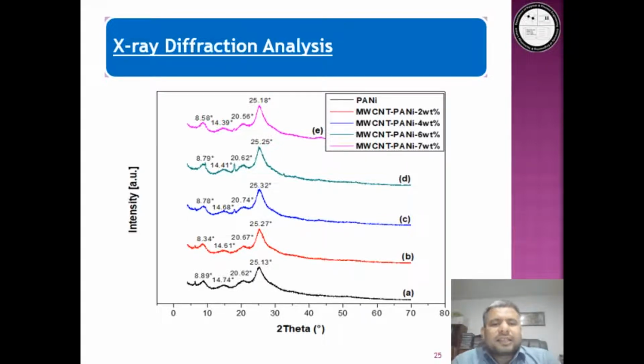The intensity of these peaks is comparatively high compared to pristine PANI, owing to structural ordering of the PANI on multi-wall carbon nanotube surfaces. So it also confirms the adhesion between PANI and multi-wall carbon nanotubes as confirmed by SEM images. Similarly, sharp peaks at 25 degree and 26 degree have also been observed for 4%, 6%, and 7 weight% multi-wall carbon nanotube composites. The minor broadening of peaks of composites could be attributed to the formation of nanocomposites.